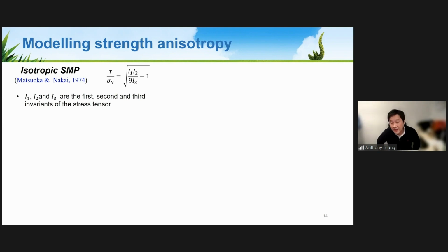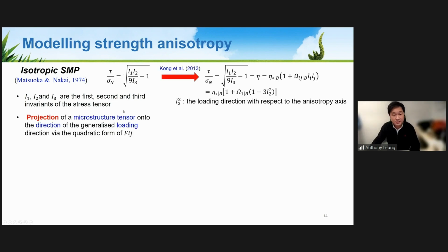So talking about the failure criterion, we adopted this Matsuoka and Nakai isotropic spatially mobilized plane model. So this equation is to describe an isotropic soil, talking about the stress ratio or shear stress and the normal stress. So what we did here is to modify this isotropic failure criterion to be anisotropic using Kong et al. 2013 approach. Basically, it is to project the microstructure tensor onto the direction of the generalized loading direction in that particular form. So in other words, you can see this eta, which is an anisotropic parameter to describe the soil microstructure.